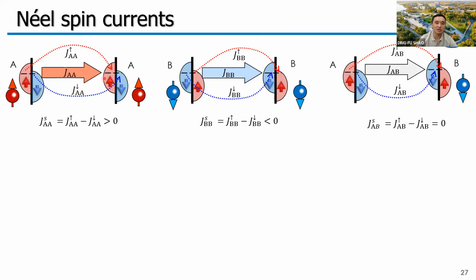Since the atoms within the same sublattice will have the same spin splitting in the density of states, JAA and JBB must be spin polarized, and we should expect their spin polarizations to be opposite. But the atoms in different sublattices will have the opposite exchange splitting in the density of states. So JAB should usually be spin neutral. The strengths of these currents are determined by the hopping between the atoms.